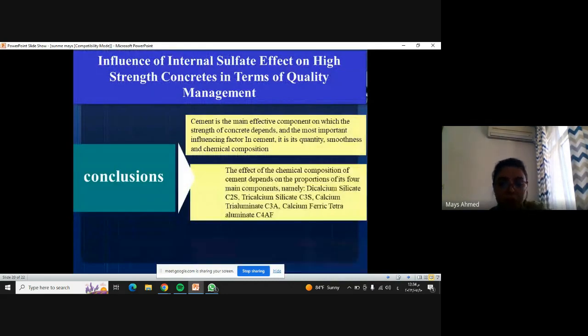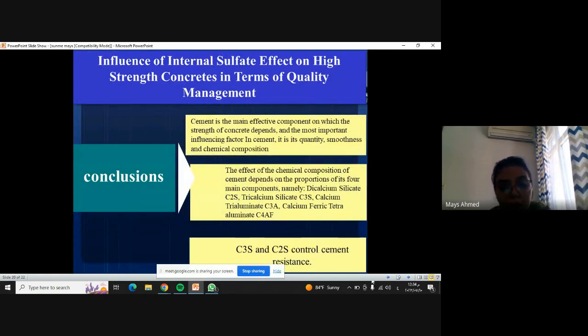Now, conclusion. Cement is the main effect compound on which the strength of concrete depends, and the most important influencing factor in cement is its quantity, smoothness, and chemical composition. The effect of chemical composition of cement depends on the proportion of its four main components, namely dicalcium silicate (C2S), tricalcium silicate (C3S), tricalcium aluminate (C3A), and tetracalcium aluminoferrite (C4AF). C3S and C2S control cement strength. This is the most important material in the cement mixture.